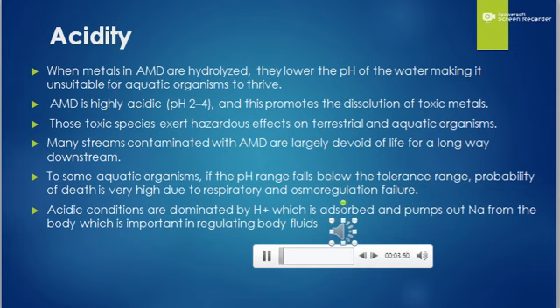Acid-mine drainage. When metals in acid-mine drainage are hydrolyzed, they lower the pH of water, making it unsuitable for aquatic organisms to thrive. Acid-mine drainage is highly acidic, pH range 2 to 4, and this promotes the dissolution of toxic metals. These toxic species exert hazardous effects on terrestrial and aquatic ecosystems. Many streams contaminated with acid-mine drainage are largely devoid of life for long way downstream. To some aquatic organisms, if the pH range falls below the tolerance range, probability of death is very high due to respiratory and osmoregulation failure. Acidic conditions are dominated by protons, which are adsorbed and pump out sodium from the body, which is important in regulating body fluids.